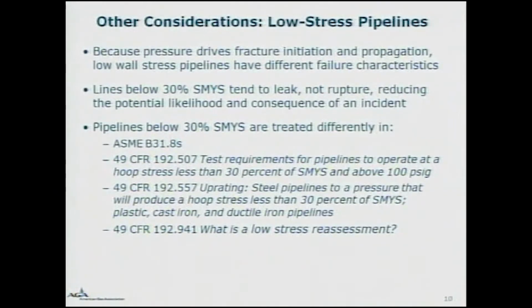Other considerations for operators include assessments of low-stress pipelines or pipelines operating at less than 30% of specified minimum yield strength. Low wall stress pipelines have different failure characteristics than pipelines operating at high stress levels. They tend to leak rather than rupture, and it is unlikely that a fracture in a low-stress pipeline will propagate. These differences significantly reduce the potential likelihood and consequences for such pipelines in comparison to the higher stress lines. As such, these differences are recognized for pipelines that operate below 30% of yield in both ASME B31.8S and 49 CFR 192.